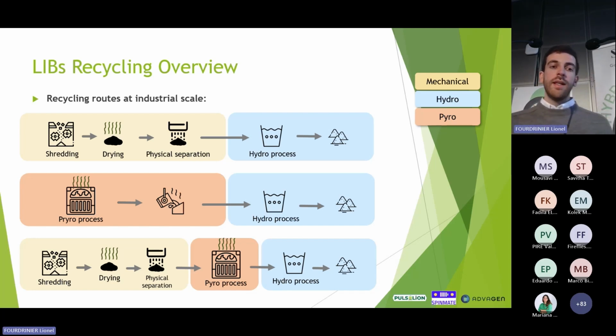So from the shred material, the fraction with the smallest particle size below 100 micrometers contains the anode active material and the cathode active material, and it's what in the recycling industry we call the black mass. So the black mass is black powder that contains the graphite and the cathode materials, and it can be separated from the rest of the shred materials by particle size, by sieving. After this, this black mass goes to the post-treatment, to the hydrometallurgical process.